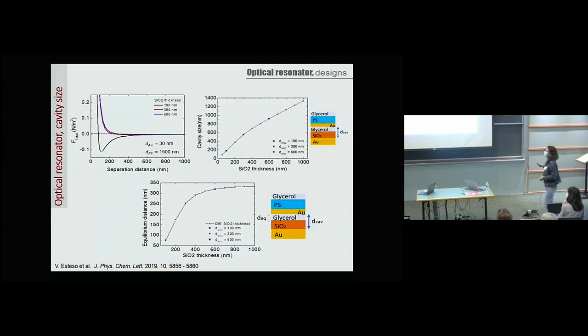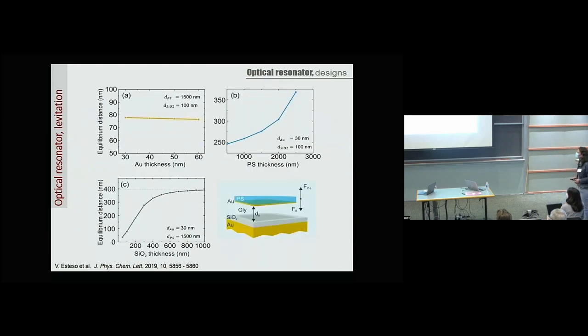So this is it. We compute the total force. We look for the zeros here. We have the cavity size, and then we have the equilibrium distance, because the cavity also contains the silica film. And we could manipulate or tune the separation, or the equilibrium distance, by modifying all these geometrical parameters here. We modify the gold thickness, the polystyrene film thickness, or the silica thickness, and then we could tune the equilibrium distance from 50 nanometers to 400 nanometers, for instance.